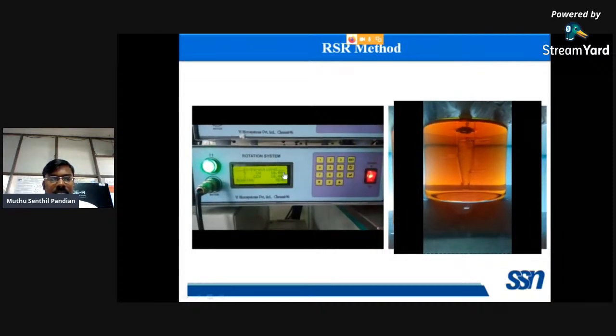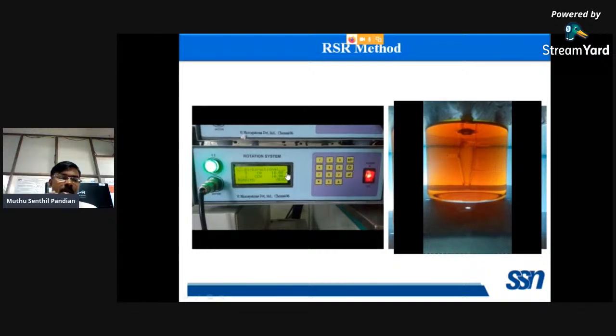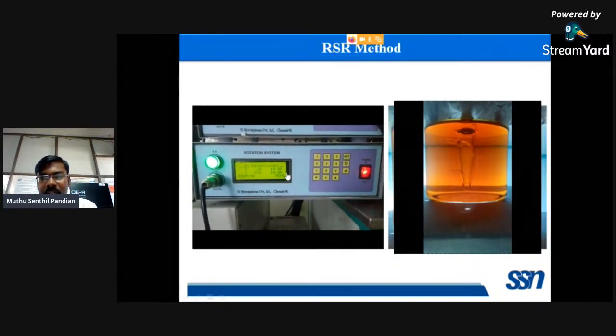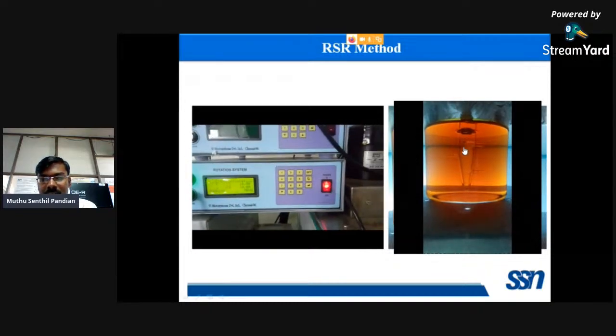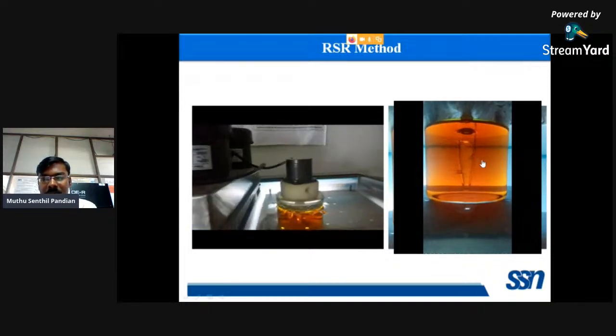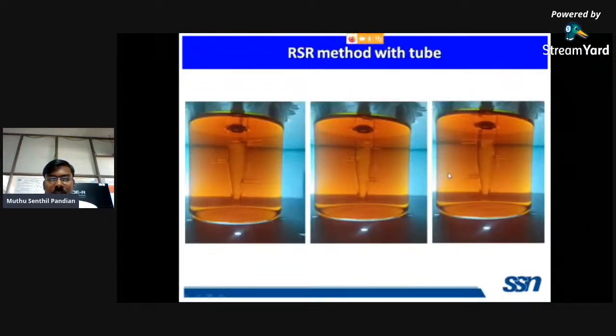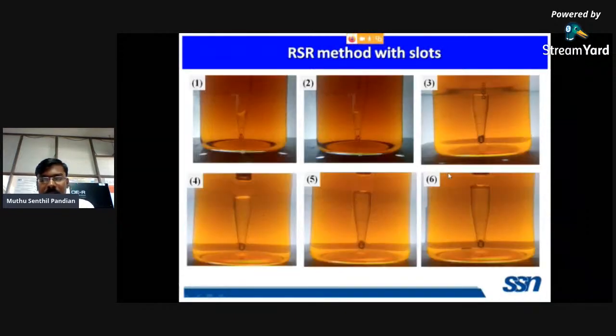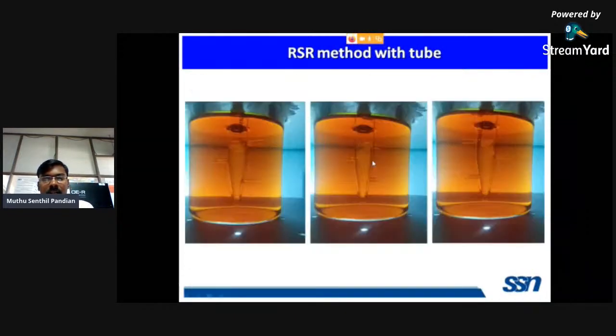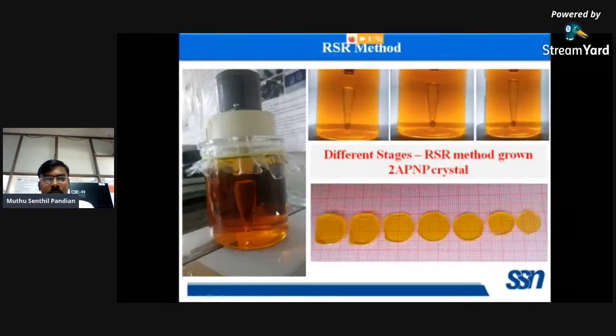So here also we have faced one problem. There is some spurious nucleation at the top. In order to avoid that spurious nucleation, we have now modified the SR glass tube like this. So there is no disturbance in the RSR method. And this is the crystal grown by RSR method with the slot, and this is the crystal grown by RSR method with the tube. So this is the slotted ampoule RSR method.